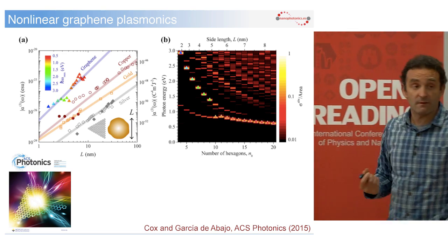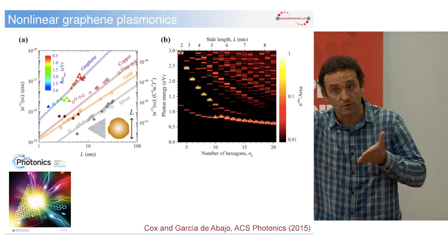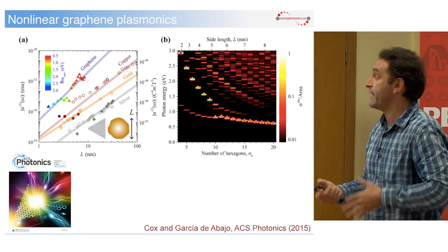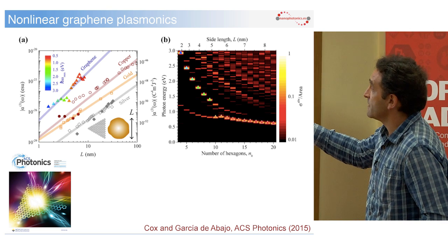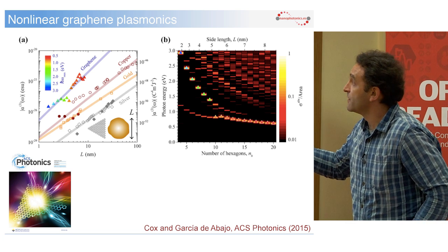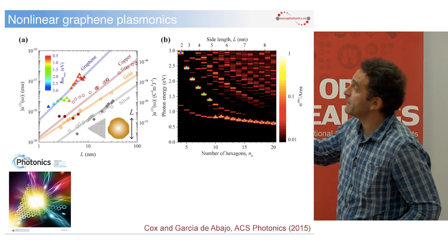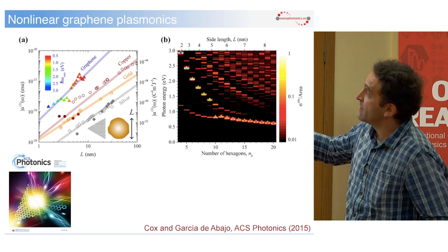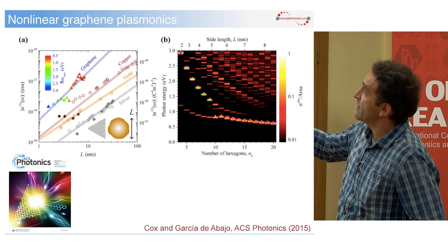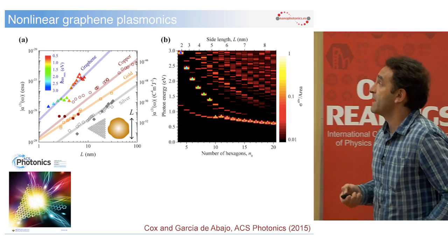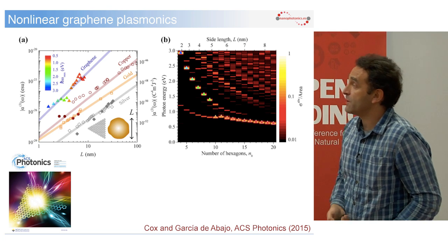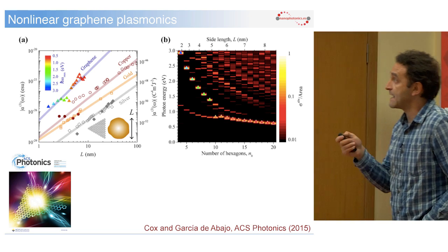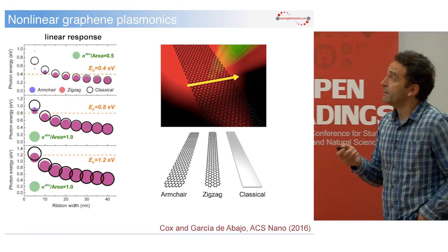Okay, but the material is not homogeneous. It can have atomistic effects, and this is what we explore here. So if you consider the edges of the structure, then something happens when the plasmon energy goes above the Fermi energy, the doping Fermi energy, and then the plasmon gets essentially destroyed in realistic calculations, essentially by coupling to edge states.